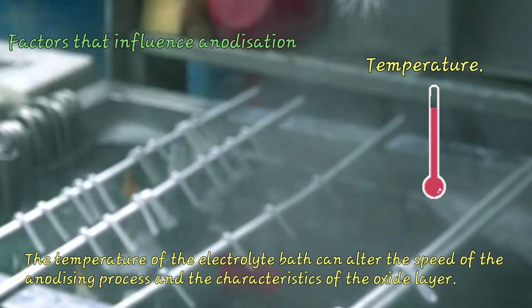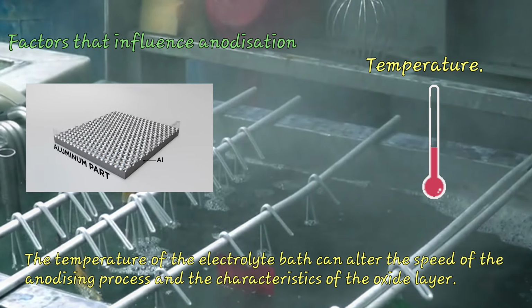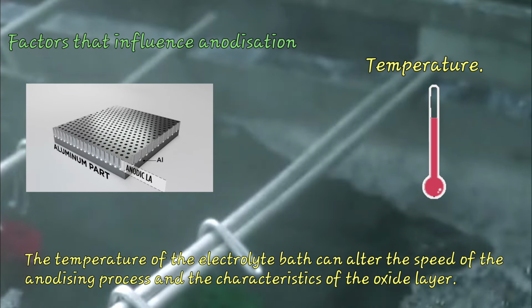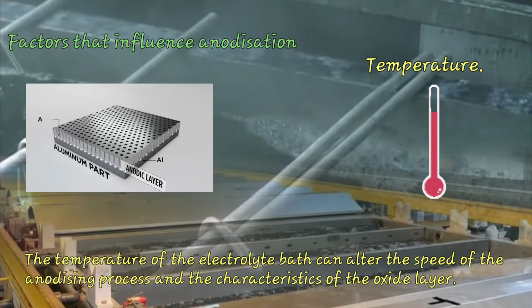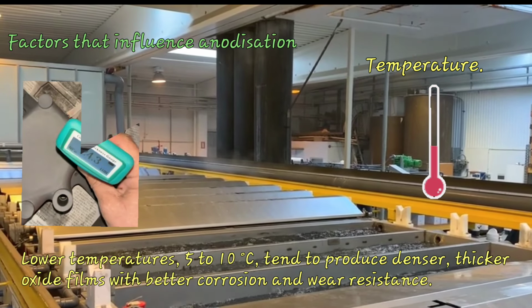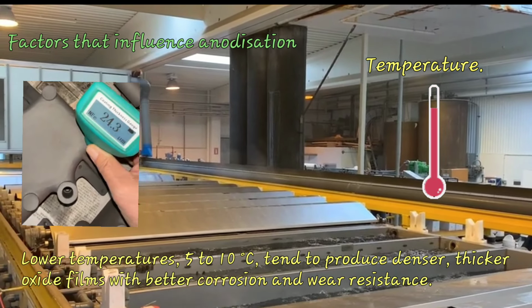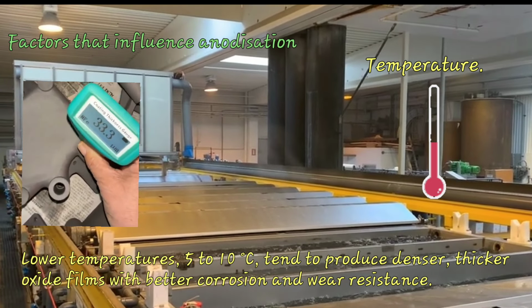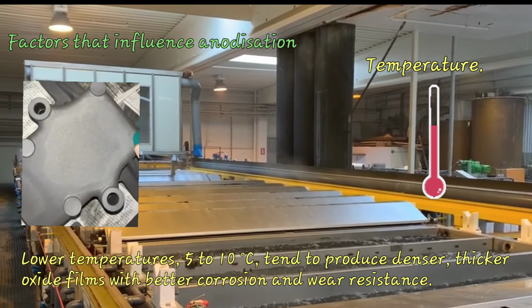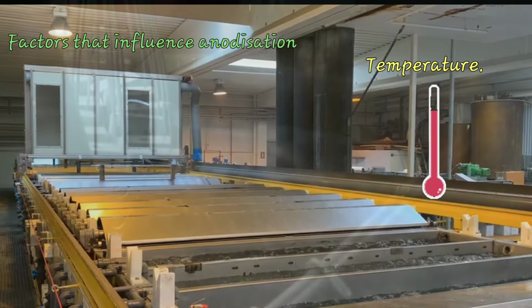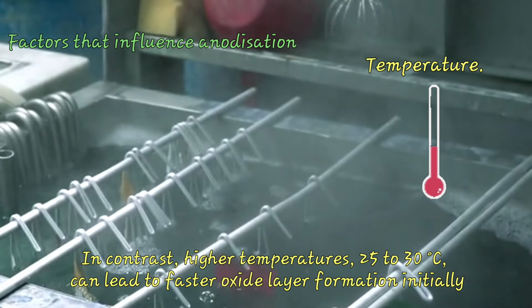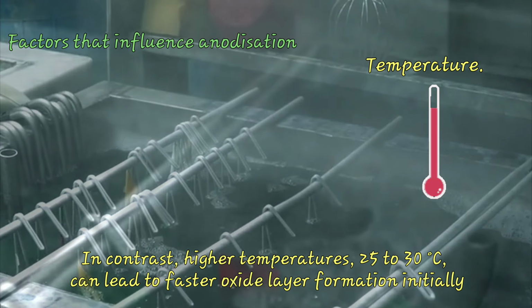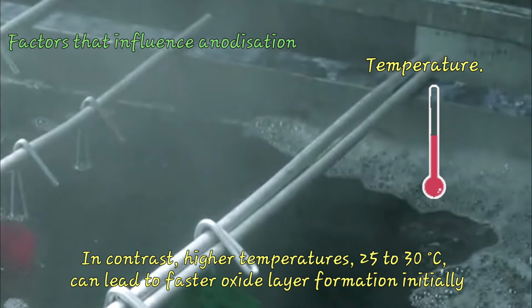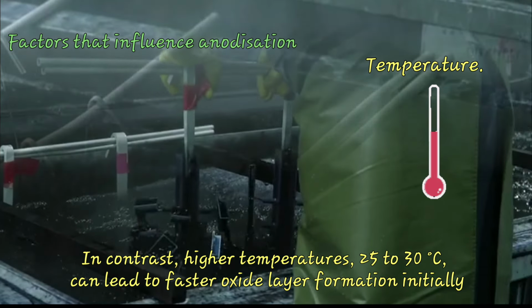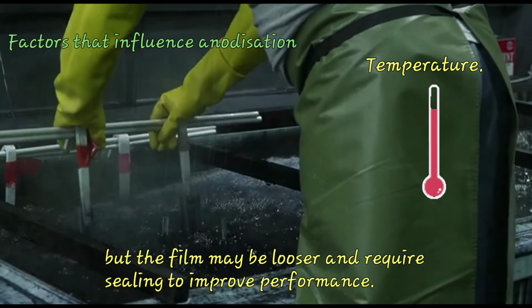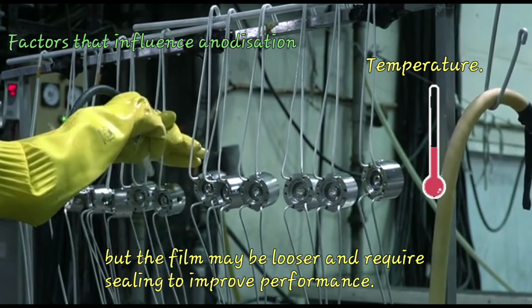Temperature. The temperature of the electrolyte bath can alter the speed of the anodizing process and the characteristics of the oxide layer. Lower temperatures, 5 to 10 degrees Celsius, tend to produce denser, thicker oxide films with better corrosion and wear resistance. In contrast, higher temperatures, 25 to 30 degrees Celsius, can lead to faster oxide layer formation initially, but the film may be looser and requires sealing to improve performance.